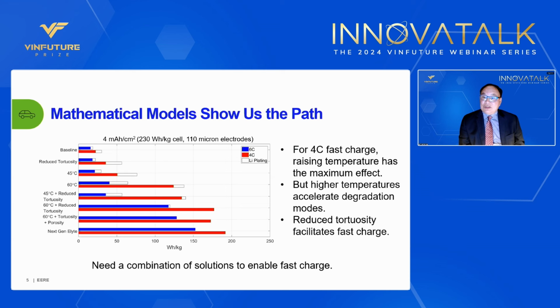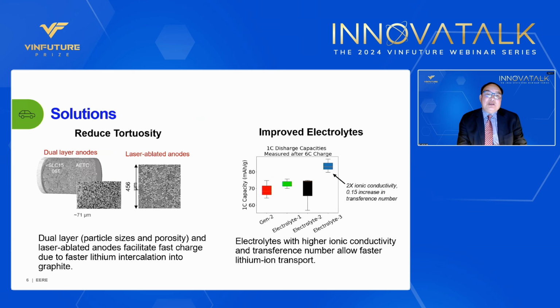However, higher temperatures accelerate degradation modes. Another point we would like to make is that reduced tortuosity facilitates fast charge. So to facilitate fast charge, we need a combination of solutions. And that's what we discussed in the next slide. The first thing you want to do is to reduce tortuosity. You can do that by two different processes. The first process on the left-hand side is to have a dual layer anode. So what you do is you have a layer of electrode with larger particles, larger porosity inside, and you coat another layer of electrode